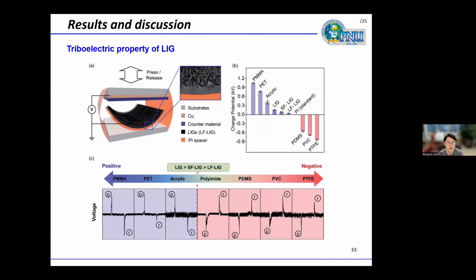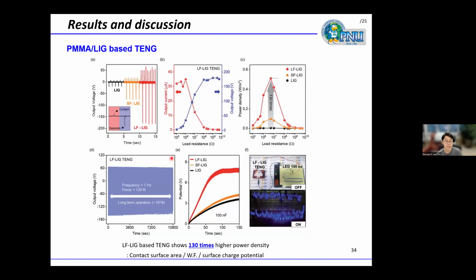We implemented a nanogenerator using this fibrous LIG electrode. By comparing the triboelectric series with the work function of LFLIG, we identified PMMA as the most suitable counter electrode. Accordingly, we fabricated the nanogenerator device using these material combinations. This slide shows the performance of the nanogenerator based on the fibrous structure LIG and PMMA as the counter electrode. As shown in this figure, LFLIG exhibits approximately 130 times higher output performance compared to the porous LIG.